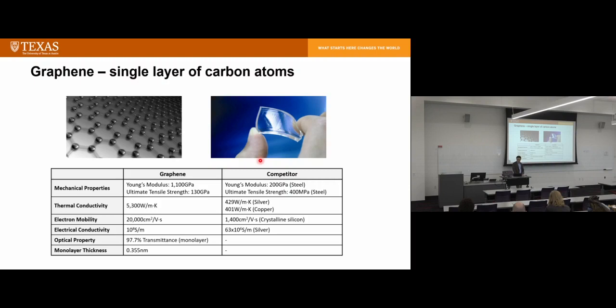For comparators, steel has a modulus of 200 gigapascal. Thermal conductivity is 429 watts for silver and 400 watts for copper. Electron mobility is 1,400 for crystalline silicon. And electrical conductivity is only 63 times 10 to the 6. If you just hear from the material scientists, they will say, okay, this graphene is so nice, the properties are so high compared to competitors, but we need to take this with a grain of salt.